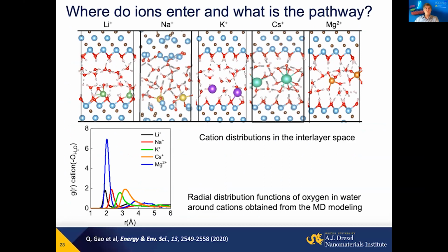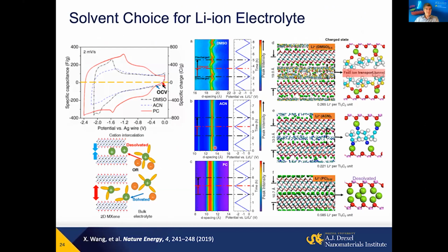But what we need to do is to understand how ions behave inside. For example, modeling simulation done by colleagues from Oak Ridge National Lab and UC Riverside showed that lithium and sodium in aqueous solution will come close to the MXene surface. There will be some charge transfer, while some other ions like magnesium and cesium will stay solvated between the layers. And if we take organic solvents, some of the solvents we consider to be very good for supercapacitors, for example, acetonitrile, giving highly conductive solutions,